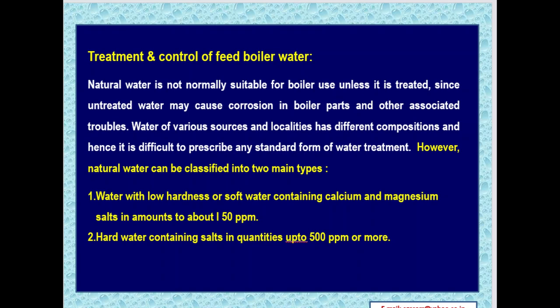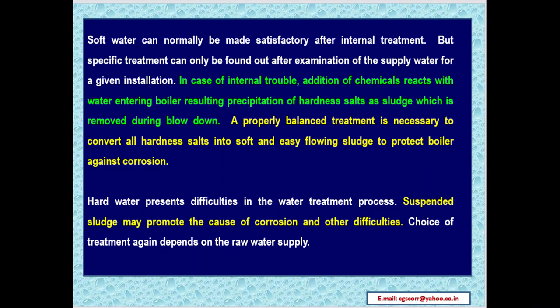1. Water with a low hardness, or soft water, containing calcium and magnesium salts in amounts of about 150 ppm. 2. Hard water containing salts in quantities up to 500 ppm or more. Soft water can normally be made satisfactory after internal treatment, but specific treatment can only be found out after examination of the supply water for a given installation.